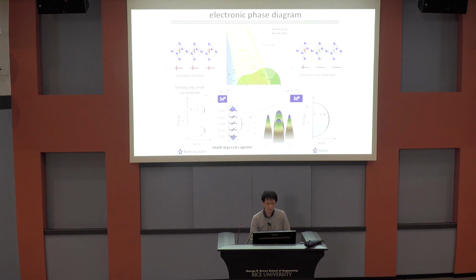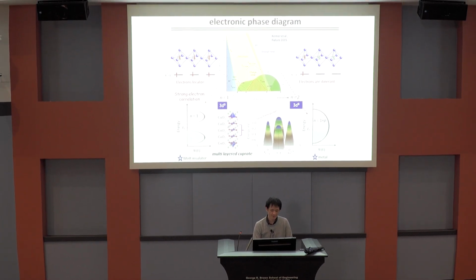Recently, we observed this small pocket by studying multi-layered cuprate. This pocket was found to appear in the protected inner layer of a multi-layer system.